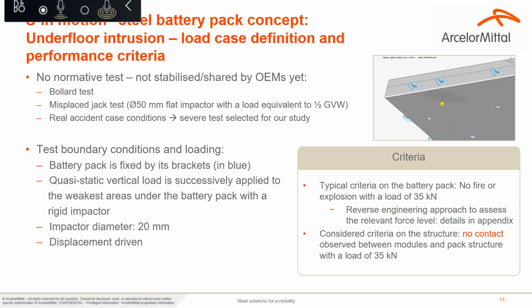The second load case is intrusion from below. For this condition, there is no normative test yet. The state of the art is not stabilized yet. We can find bollard tests or misplaced jack tests, where you misplace your jack and you push with half of the gross vehicle weight on an impactor of 50 millimeters. These were not found to be the most damaging condition.